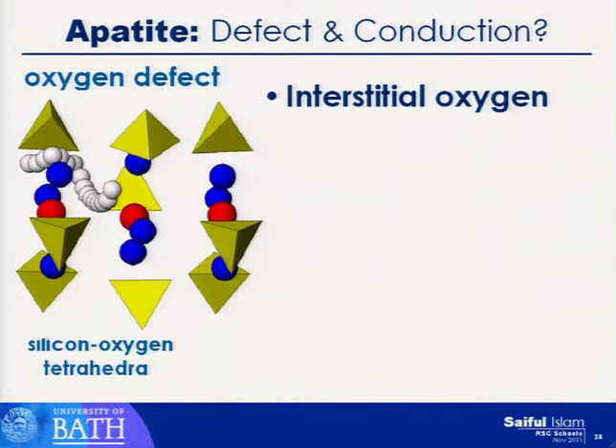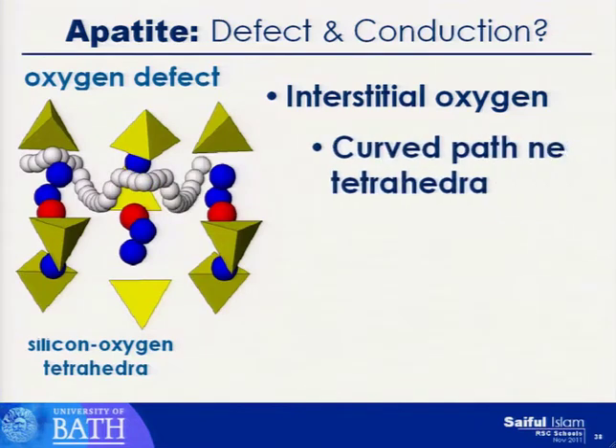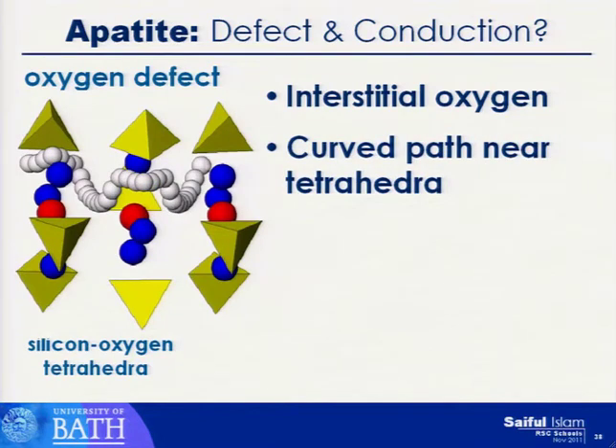And the next surprise was that we predicted that the path would not be linear, but a very curved, sinusoidal path down the channel, where the tetrahedra allow that. So, a curved path near the tetrahedra. What was nice is that neutron diffraction confirmed the position of that defect. So our modeling was confirmed by experiment. What experiment hasn't been able to do unambiguously is this curved path. But we feel confident that we've got the energetics and everything quite right.